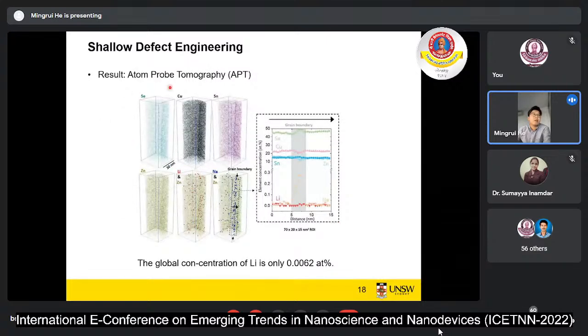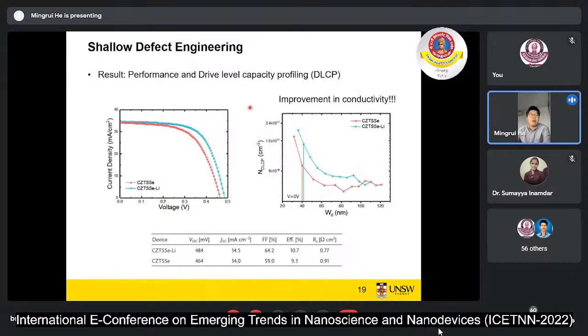After that, we did the APT, which can observe at the atomic scale how the elements are located. Here we observe that the lithium is located throughout the bulk of the CZTS, with no pattern at the grain and grain boundary. But the lithium concentration is quite low. Once we confirmed the lithium is in the bulk of the kesterite, we measured the IV curve, the device performance. We can observe the efficiency of the CZTS has improved, through the VOC, JSC, and fill factor, the three parameters that determine the efficiency of the solar cells.